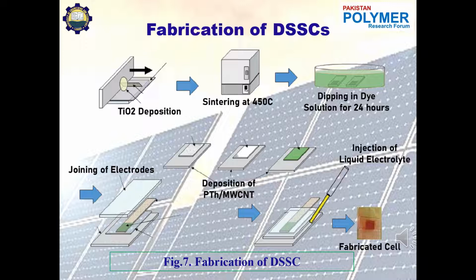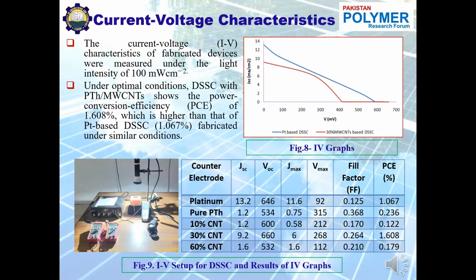IV characterization was done. Current voltage characterization of the fabricated cells was done with the help of the instrumentation shown in the figure, and the light intensity was 100 milliwatt per centimeter square. Under optimal conditions, the DSSC with polythiophene and MWCNT shows a power conversion efficiency of 1.608, and the fill factor was 0.264, whereas the platinum-based cell showed an efficiency of 1.067 and a fill factor of 0.125, fabricated under similar conditions.